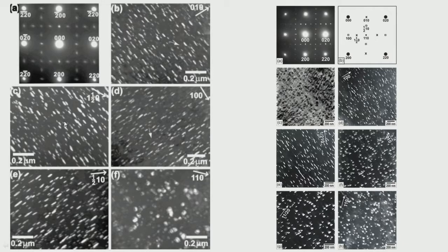That same thing happens here with 100. So try to image with as many reflections as possible. Now we are able to differentiate and tell that these spots, this one and this one, and these three reflections, that is 100, 010 and 110, they match with both this phase. One is called gamma prime, another is called gamma double prime.